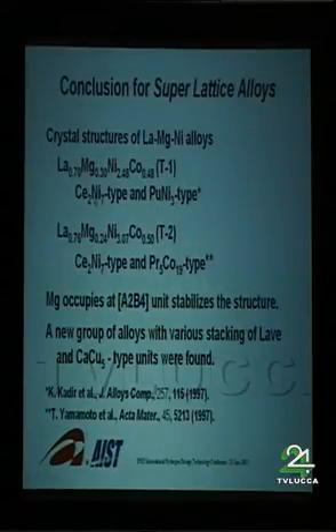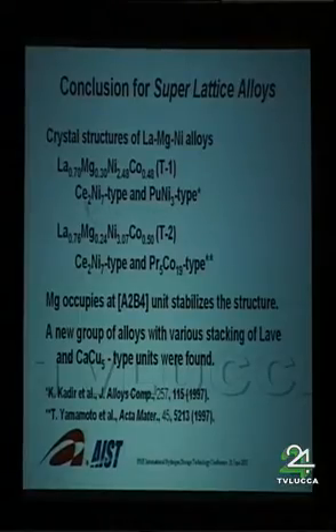It's very, very long. And we found three different types of stackings in two alloys. So in one alloy, we found this type and this type, Ce2Ni7 type and PuNi3 type crystal structures. And this type, Ce2Ni7 type and Pr5Co19 phase, was found in the other alloy. The magnesium occupies the Laves phase type unit, and this occupation stabilizes the structure for repeated hydrogenation. And new groups of alloys with various stackings of Laves and AB5 type units were found in this study.